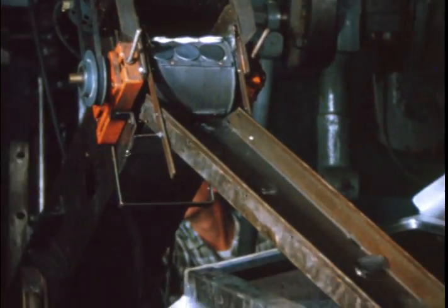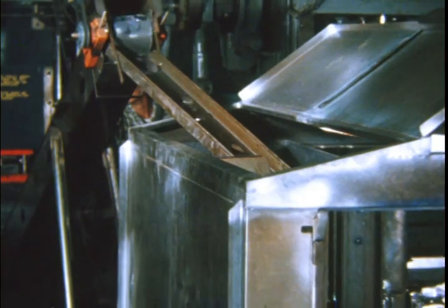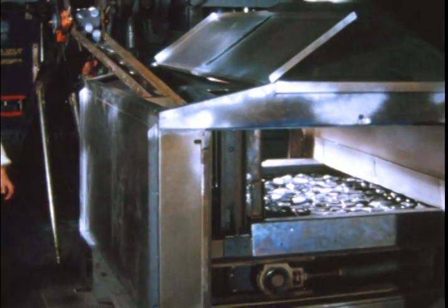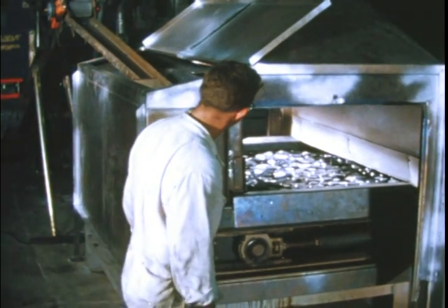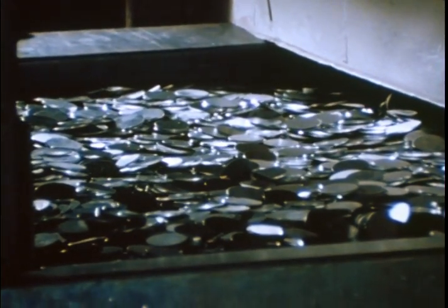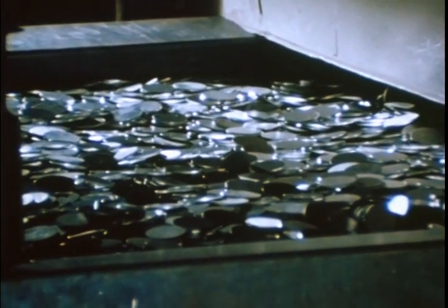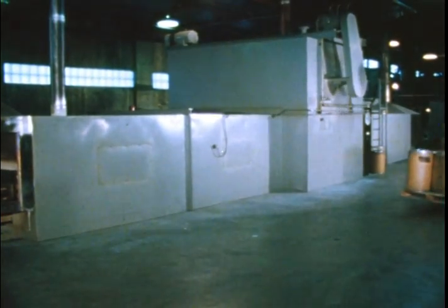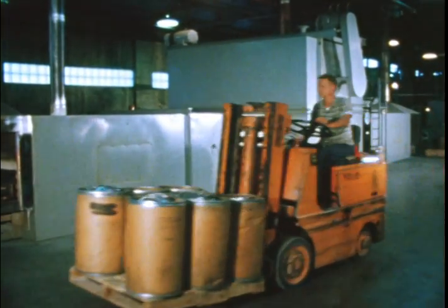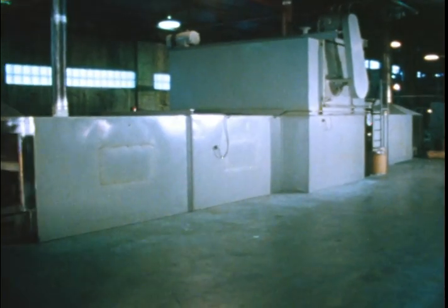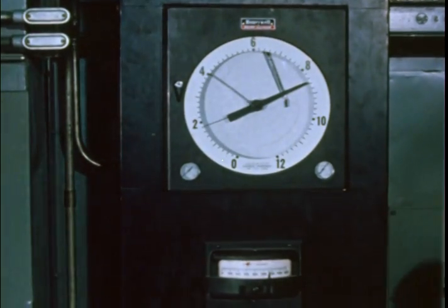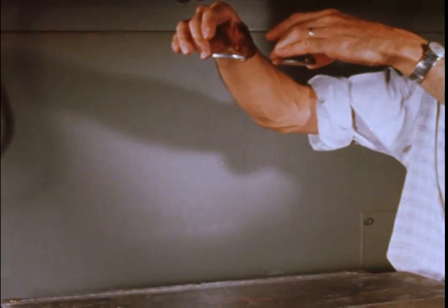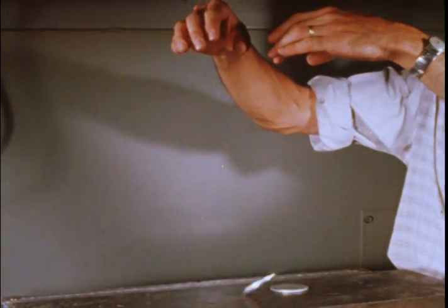The slugs are conveyed to an annealing furnace where they undergo 1 hour at 900 degrees Fahrenheit to soften them for the subsequent extrusion process. This is an overall view of our annealing furnace. The drop test, here shown in slow motion, is a good way to determine whether a slug has or has not been annealed. You will note the higher degree of elasticity on the unannealed slug on the left.